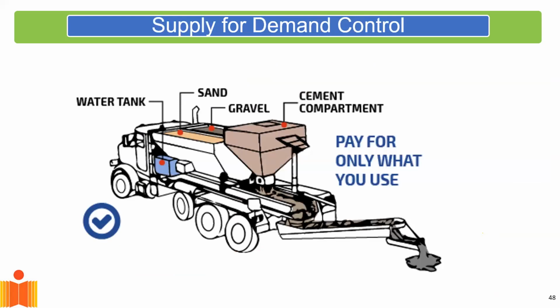Now, of course, we're talking about making concrete, and now more and more there's talk of this concrete in micro quantities. So here, this is like a mobile concrete delivery system, where I can vary the composition of this even for small dosages. So as I'm placing concrete, I can vary the properties of concrete in the different layers as I'm depositing it by doing a local control here. So you're talking about injecting materials at the delivery point and locally altering the material so that I get variable properties at the local level. So I can now even start thinking about placing variable strength concrete if I need it within the same structural element. So that is what people are now starting to talk about when it is about delivery systems.